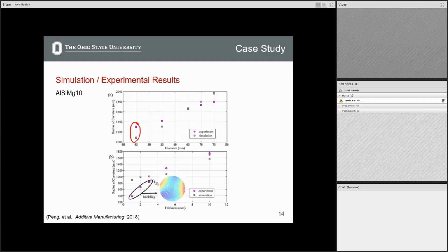When you start to get very, very thin samples, you have to keep in mind what the aspect ratio is. This is a 1 millimeter thick disc that's 45 millimeters in diameter. It's basically a really wide washer. We would see in the CMM that we're starting to get buckling in these types of parts. This is getting some sort of asymmetry in the deformation behavior, which wasn't explained by our model. So this is a region in which our model doesn't seem to work so well.